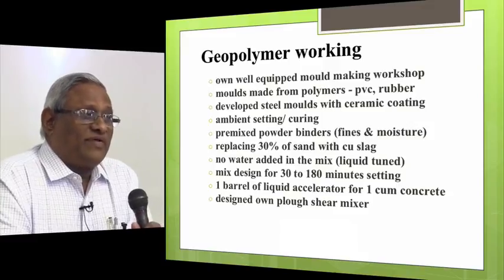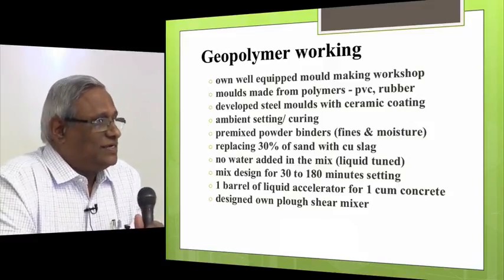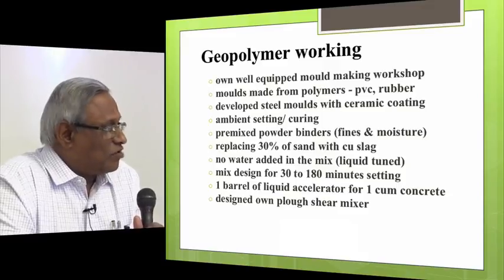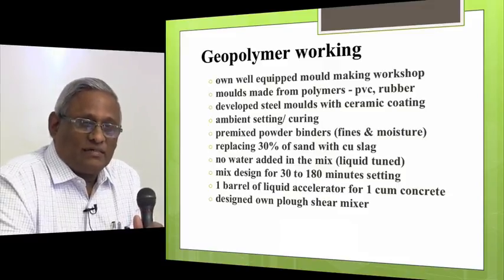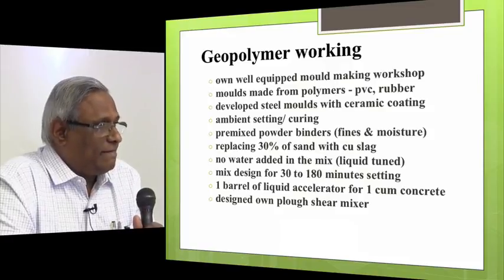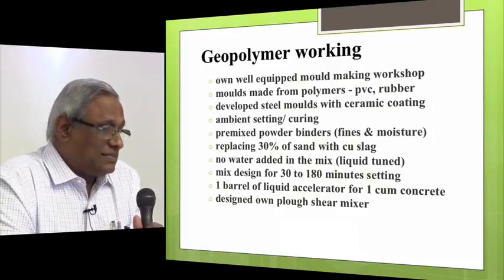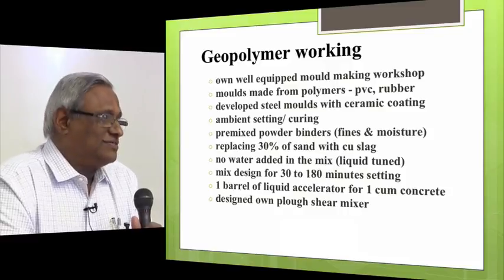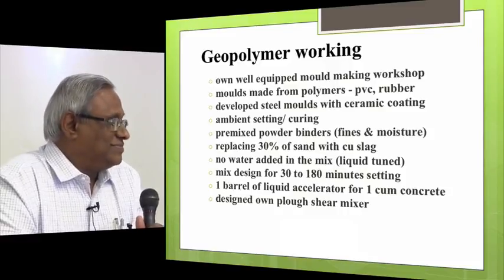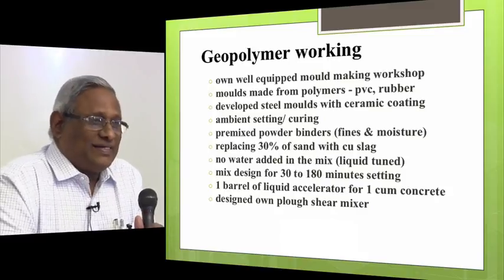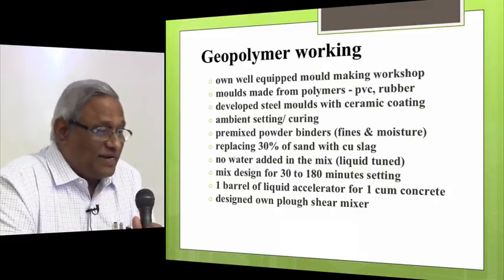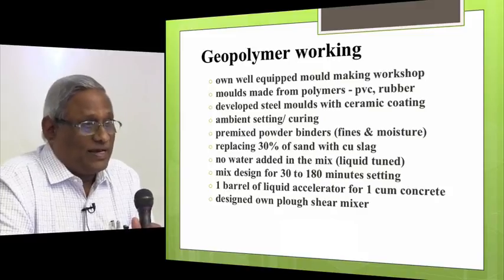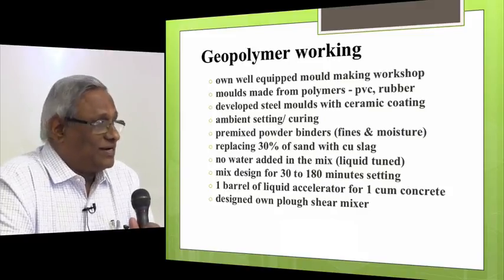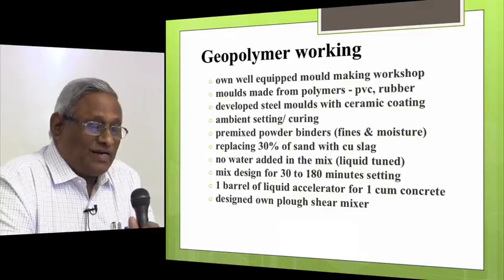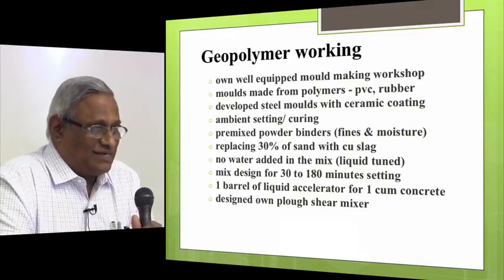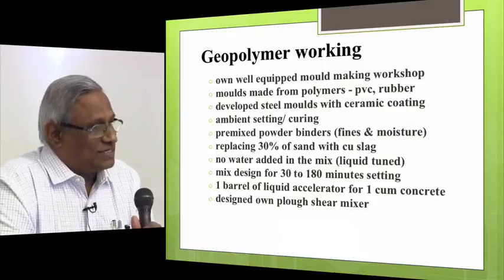We are able to very effectively replace 30% of the sand by using copper slag. Copper slag is available in abundance in three places in India. We were able to use it because the copper slag is literally free for us, and sand is the most expensive item. And sand mining is now restricted. So this is one very good move that we could make, and that's why we were able to make our concrete very competitive. In fact, you will wonder that now we are selling geopolymer concrete at a lower price than Portland cement concrete.